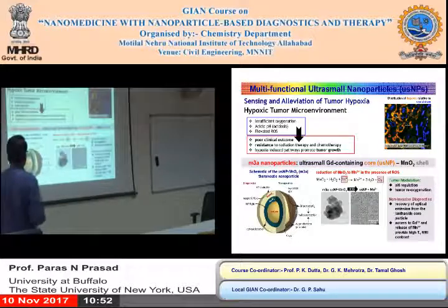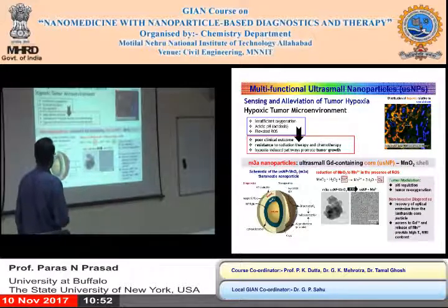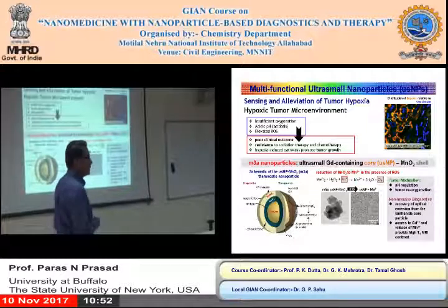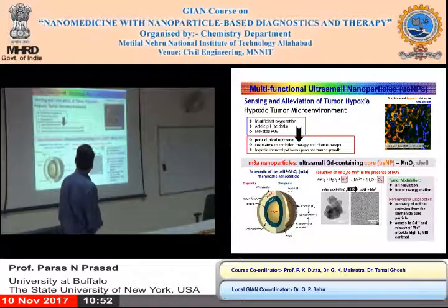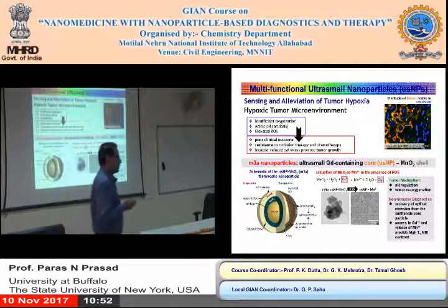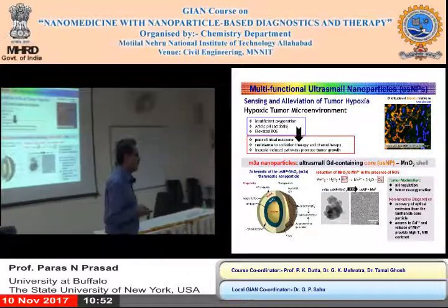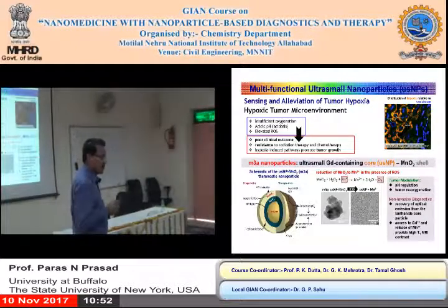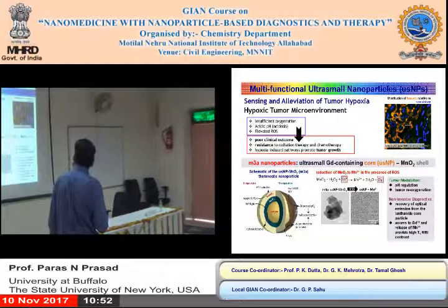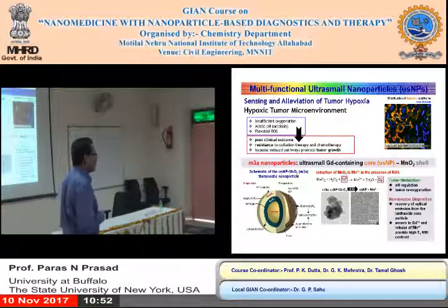The manganese dioxide, when it gets into the tumor area, which is a little more acidic, reacts with that, and there may be some peroxides or radicals, which are generally called reactive oxygen species, ROS, that are also present in the cancer area. So it reacts together and it reduces to manganese 2+, releasing oxygen.